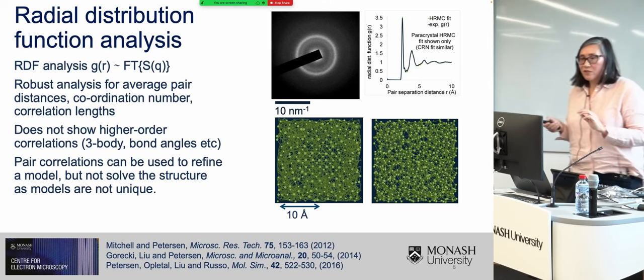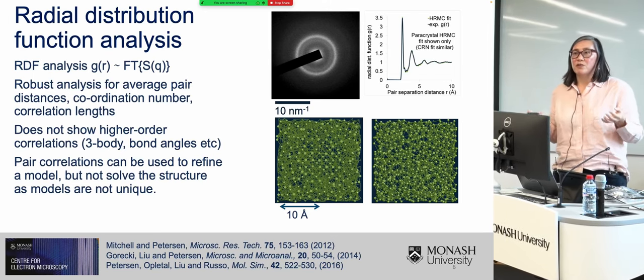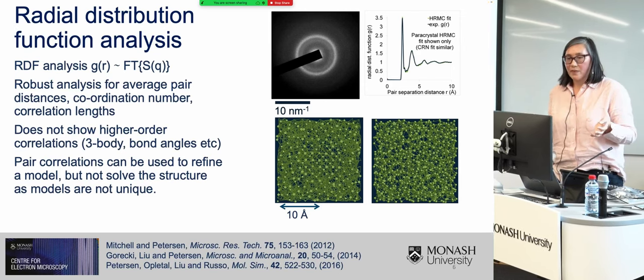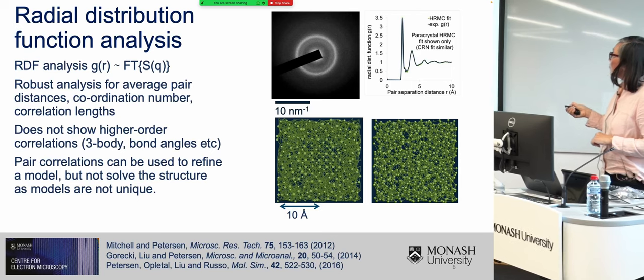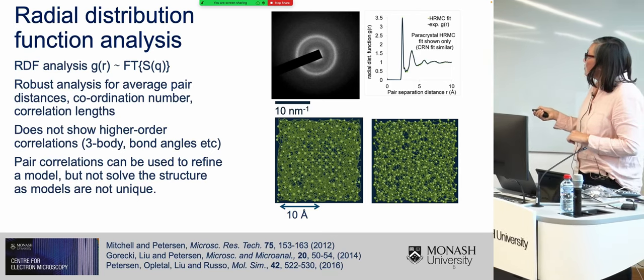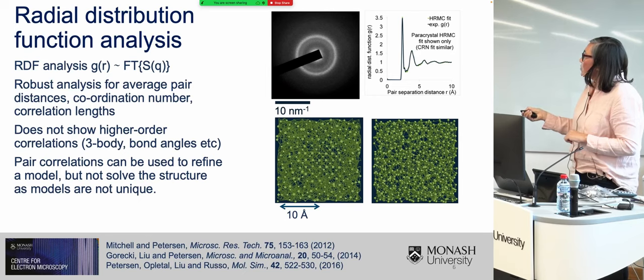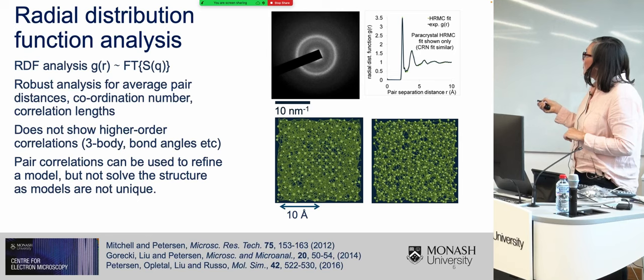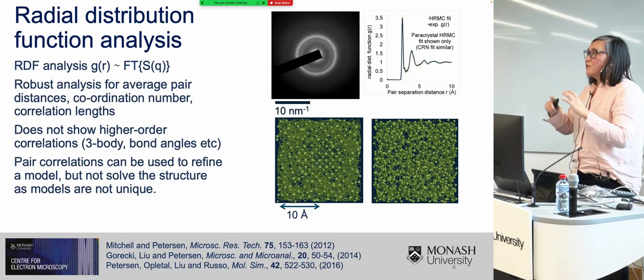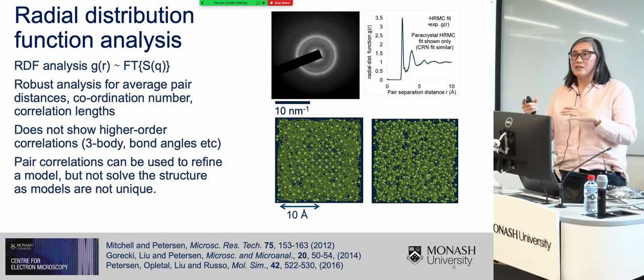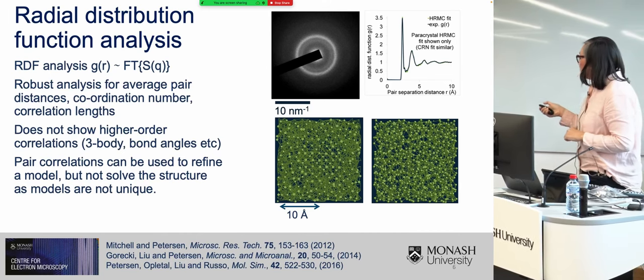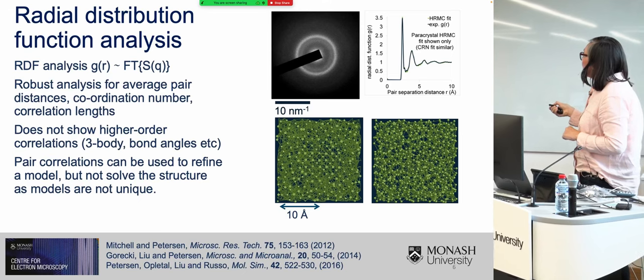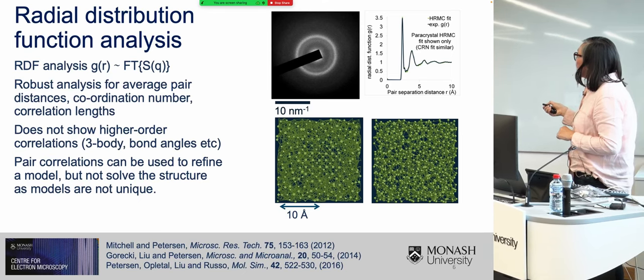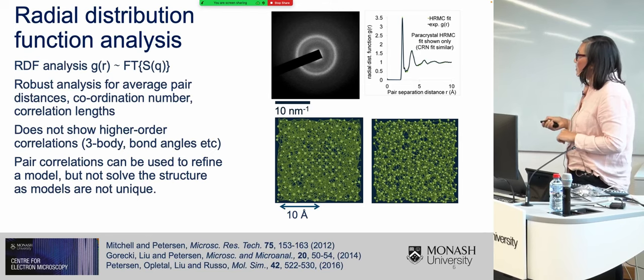Now, however, I don't want to suggest that broad beam traditional diffraction measurements on glasses tell you nothing. The broad beam diffraction pattern and the structure factor that you obtain from it are related by a Fourier transform to the radial distribution function, which I show here in the case of this amorphous silicon. And this radial distribution function tells you about the averaged pair distances in your material. So for example, you can get very robust information about the coordination, the number of neighbors in your coordination sphere, and different correlation lengths in your material.